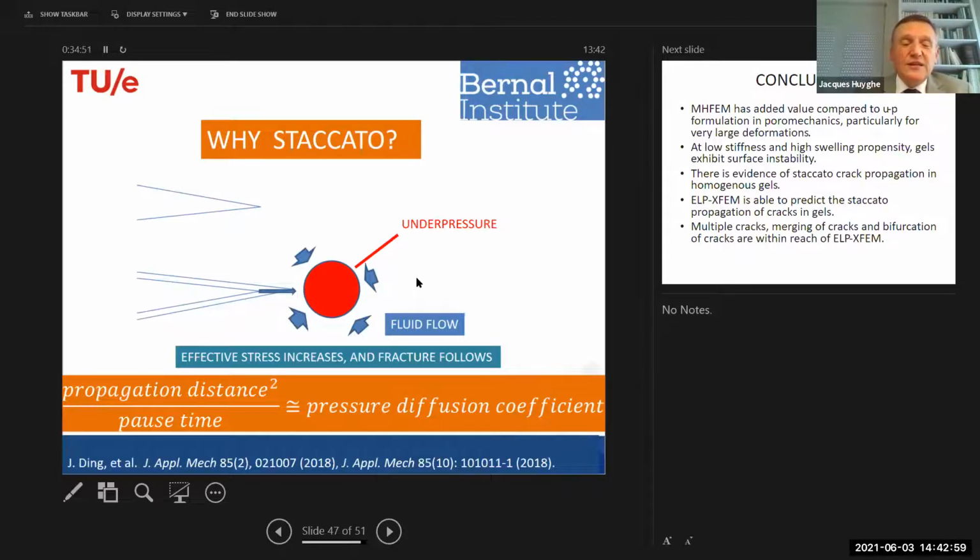And the result is that very locally you have a triaxial tensile strain on the macromolecular network of the gel. And so there the gel macromolecular network fails. After a while, each time waiting a time, propagation occurs, and then again underpressure occurs a little further, and the same procedure is happening all over again.